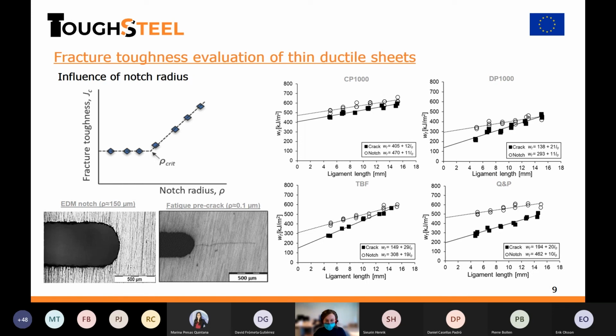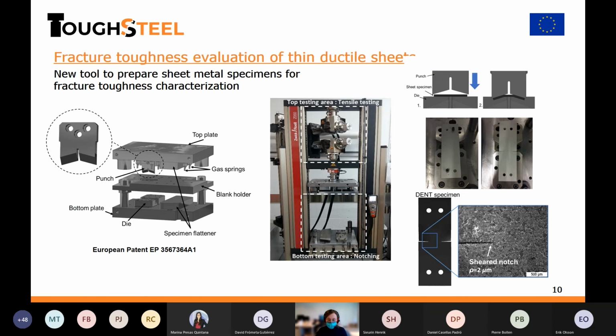And how do we get the sharp notches? First, usually we use fatigue pre-crack notches that need to be performed in specific machines for fatigue pre-cracking and fatigue experiments. So it can take quite some time to perform, and difficult techniques to process. So in EURECAT we have developed a new tool to solve this problem and make it faster and more simple and easier to apply to the industry. And it's a new tool that can create two symmetric notches to DENT specimens by a shearing process. You can see here that with the specimen created, we can get these sharp notches that are similar to fatigue pre-cracked ones.